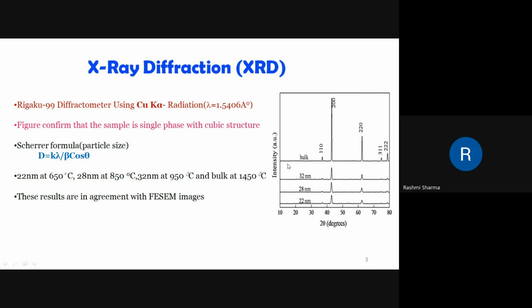In order to get the size of the particles, we use the Scherrer formula, which is D equals K lambda by beta cos theta, where D is the size of the particle, K is the shape constant, lambda is the wavelength of radiation used, and beta is the full width at half maximum of the peak, and theta is the diffracting angle. So using this Scherrer formula, we get different sized nanoparticles for different temperatures.